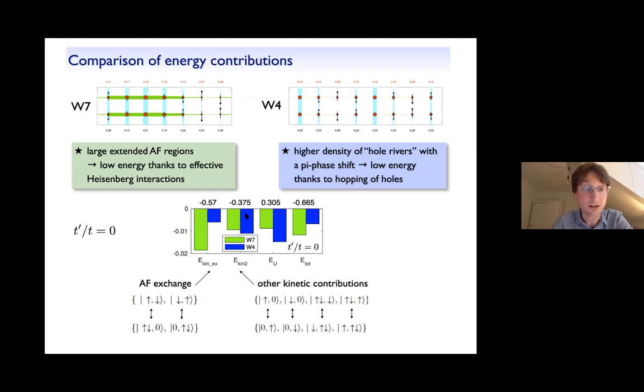And now these are the remaining kinetic contributions. Here, these are mostly the exchange of a hole with a neighboring spin. And as we argued before, you can see that this energy is lower in the period 4 stripe. But in the end, for t prime equals 0, it's this term here which is more dominant, such that the period 7 stripe wins.